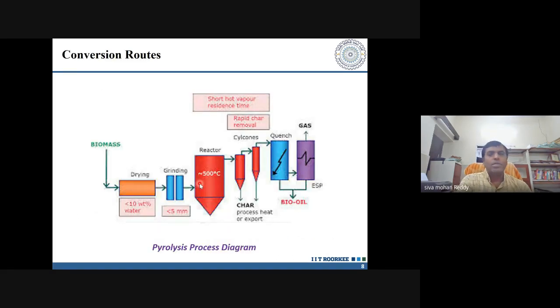Now let me give you an overview of what kinds of conversion processes are available. The most popularly used conversion technique for turning biomass into liquid fuels gives what is called bio oil, pyro oil or pyrolysis oil, which you might be well aware of. You first need to dry the biomass to make sure its moisture content is less than 10 weight%. That is where most of the energy input for the entire process goes: 80 to 90% of the energy required for converting biomass into liquid fuels in a pyrolysis plant results from the drying process.